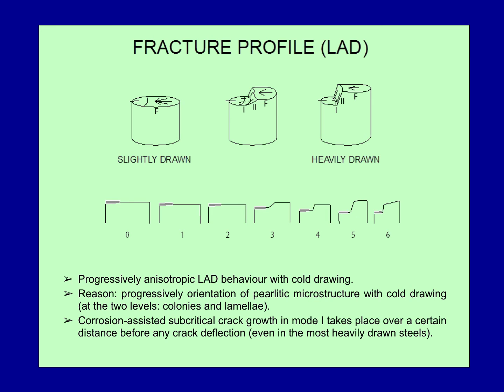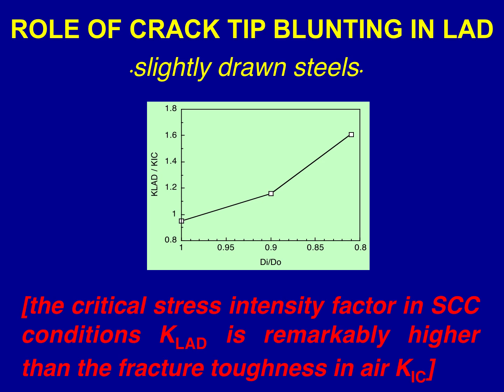We have a progressively anisotropic stress corrosion cracking behavior with cold drawing. Reason: progressive orientation of pearlitic microstructure with cold drawing at the two levels of colonies and lamellae. Then we have corrosion-assisted subcritical crack growth in mode 1 that takes place over a certain distance before any crack deflection, even in the most heavily drawn steels. That's very important. There is mode 1 propagation before crack deflection in the crack path.